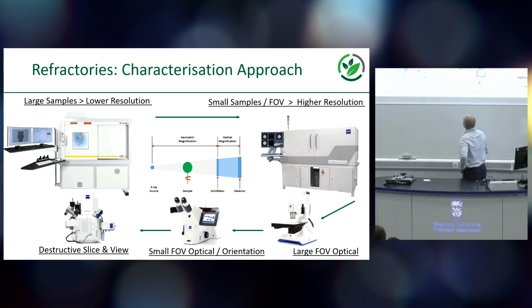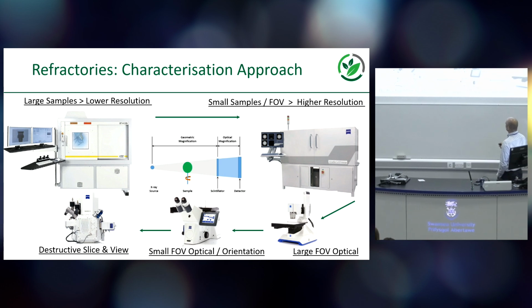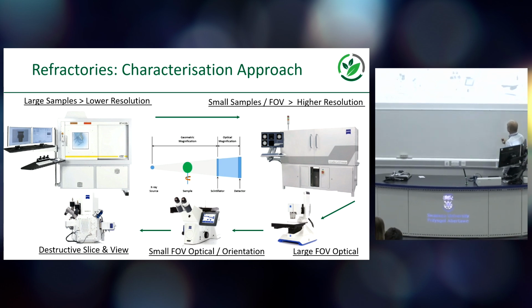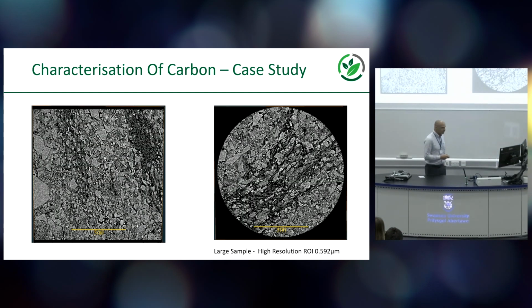Okay, so what have we done in our work? We've looked at a novel characterization pathway. So the core work funded in Sustain looked at developing a novel characterization pathway for these materials, where we looked at multimodal characterization. So we got low resolution imaging of large samples non-destructively using X-ray tomography. And then we've looked at high resolution X-ray tomography, where we can get a better idea of the structure of the materials. And then that is correlated with scanning electron microscopy work that is able to dig down into the material. I'm sort of explaining this in layman's terms, or FIBSEM for people who know what that is. And that can be correlated also with optical methods as well. And the idea is you pull all this information together to learn more than you would have done before.